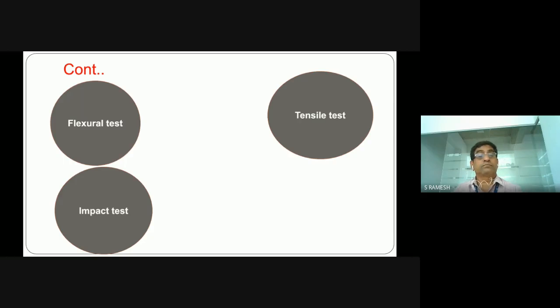And then impact test. In the impact test, we used the Izod impact test. In that, we are using the ASTM standard D256/10. The dimension of the specimen we prepared is 62.5 mm into 12.5 mm into 3 mm.